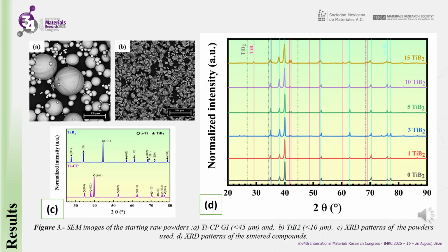As illustrated in Figure 3, the initial powders exhibited a specific morphology, and the phases present within them were identified as pure. This confirmed the absence of any contaminant phases. Furthermore, the X-ray diffraction patterns of the sintered samples are presented. The compounds demonstrate that the alpha titanium phase is the most prevalent in these sintered systems. In the case of reinforced compounds, they also exhibit characteristic peaks for titanium diboride and titanium boride, phases that increase as the amount of reinforcing particles increases.